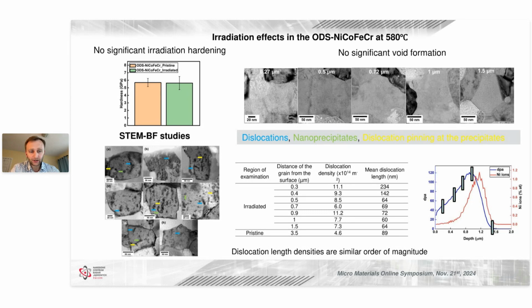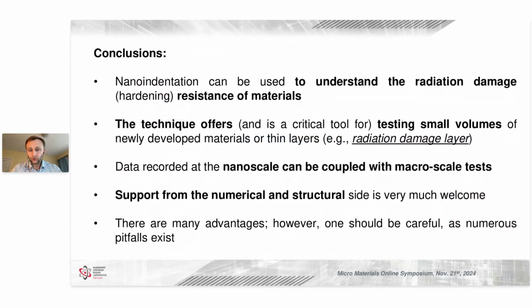And when we analyzed the microstructure following the increase of the irradiation dose, we did not see any voids in the material. So to conclude, nano indentation can be truly used as a helpful tool to understand radiation damage resistance of materials, as it allows to test small volumes.